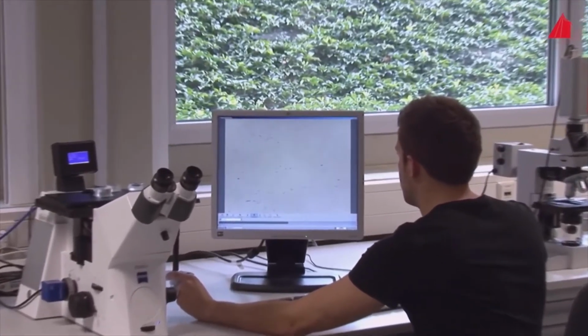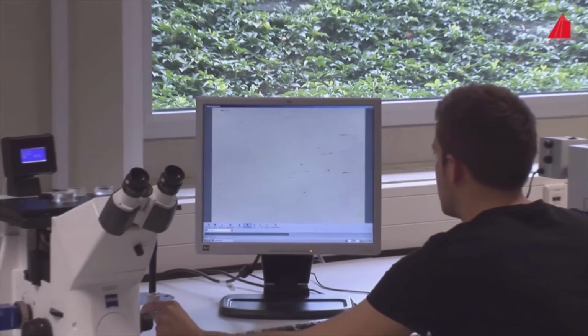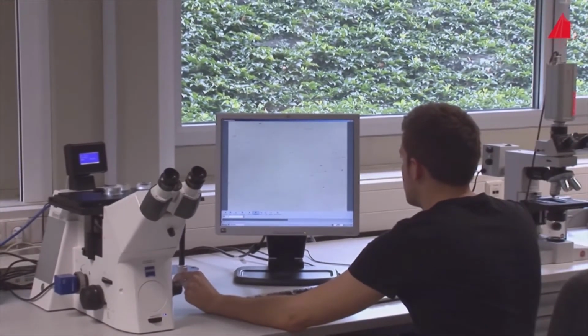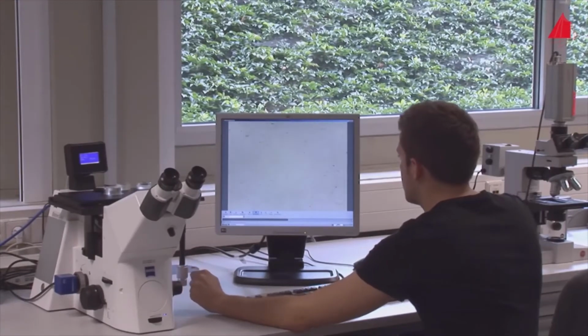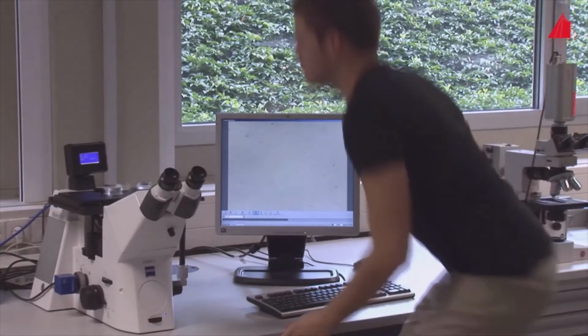Using the built-in digital camera, the polished specimen surface can be observed on the computer monitor. In the polished state, there isn't much to be seen in this material. Only some elongated non-metallic inclusions can be observed, but if these inclusions are of special interest, then the polished state is the perfect one. Inclusions may best be seen here. However, if one wants to see the crystals, the grains and grain boundaries, then the microsection has to be etched.